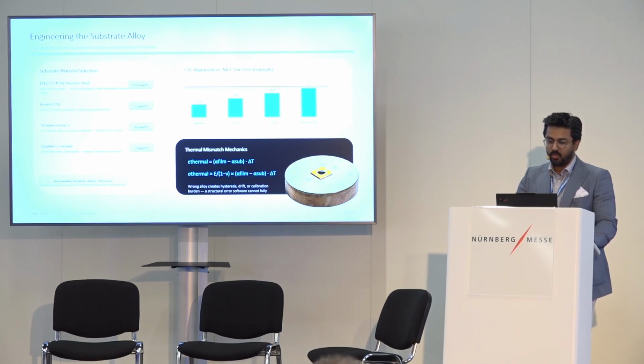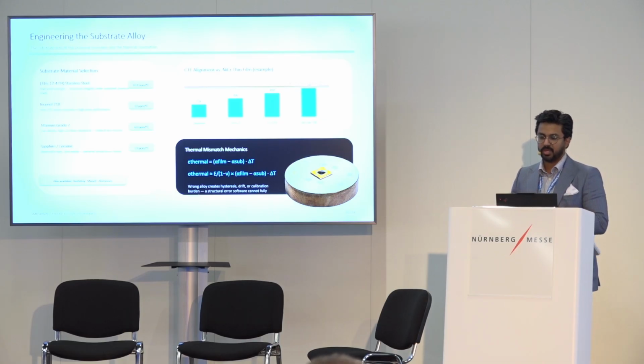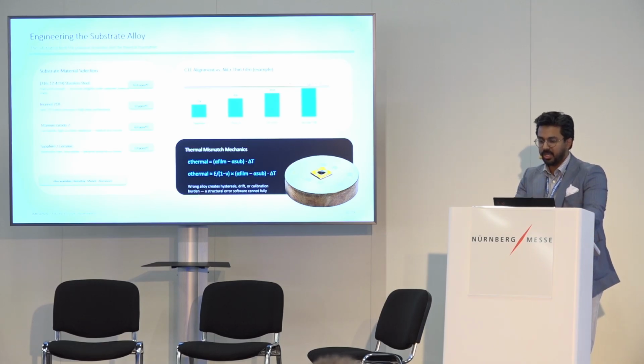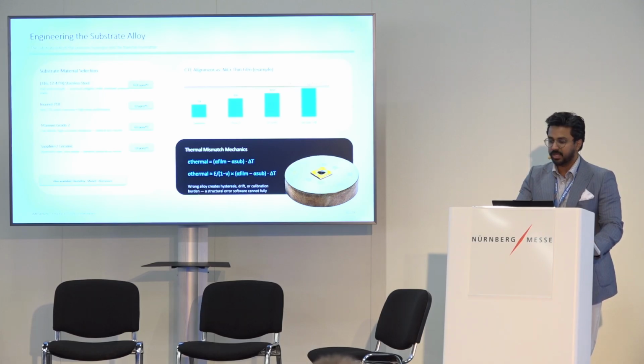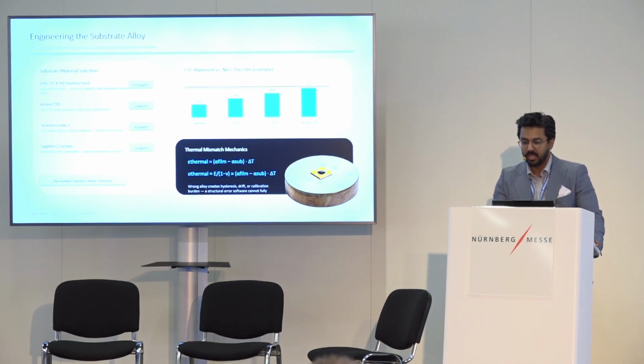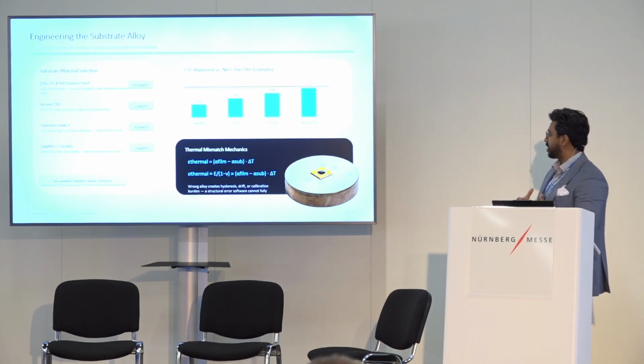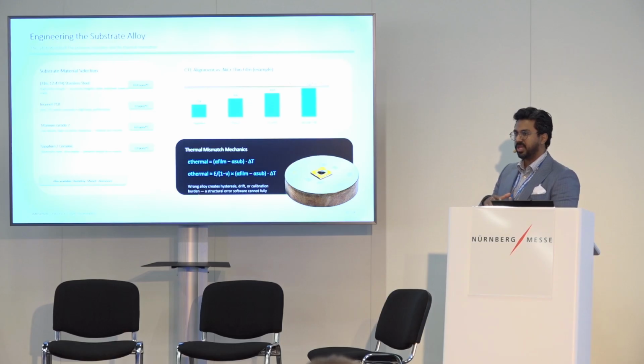At SMD, and as industrial practice, everything starts with the substrate. It does two jobs at the same time: it holds the pressure and it sets the thermal environment that the film lives in. In this slide, there are four common choices which the industry practices and which our company also uses. Inconel is our go-to for high temperature applications with corrosive media. Its expansion rate is very close to the thin film that we use, and expansion rate is very critical here because we have to manage the thermal mismatches between the mechanics of the substrate and the thin film.